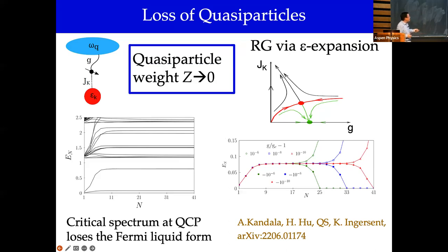And from the many-body spectrum, we can establish the existence of these actual fixed points in terms of the finite-size spectrum, and show that the finite-size spectrum, when it's here, can be reproduced through quasiparticles and quasiholes forming some combinations. When you're at this red fixed point, you cannot do that anymore. The quasiparticles are lost. It's a many-body spectrum way of making the same statement. So the critical spectrum at the quantum critical point loses the Fermi liquid description, and there's no longer a quasiparticle.